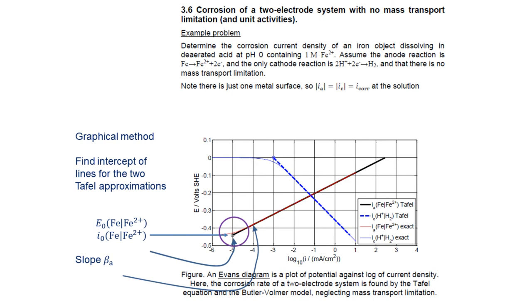The graph at the bottom of this page shows you what's called an Evans diagram, on which you could plot the Tafel equation as a graphical construction. This is equivalent to doing the algebra. The Evans diagram has log of current density along the x-axis and potential in volts against SHE on the y-axis. To construct this diagram, you would first of all say the thin red line represents the true equation 3.15 Butler-Volmer equation, telling us the net current density of the iron reaction. But we're not going to plot that. We're going to plot the thick black line, which is the Tafel approximation for that. And likewise, we'll plot the thick dashed blue line, which is the Tafel approximation for the hydrogen reaction. And we are looking for the intersection of these two lines.